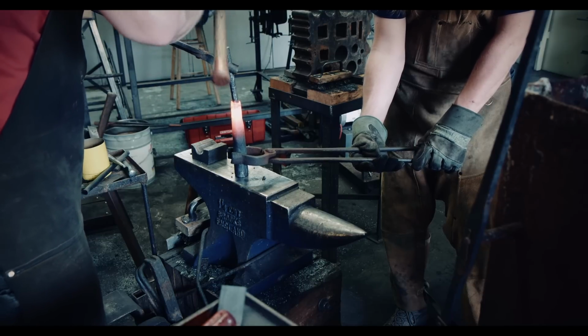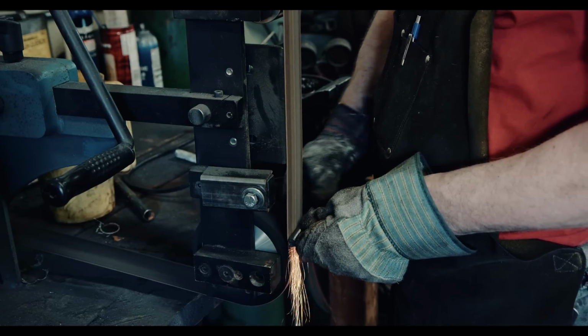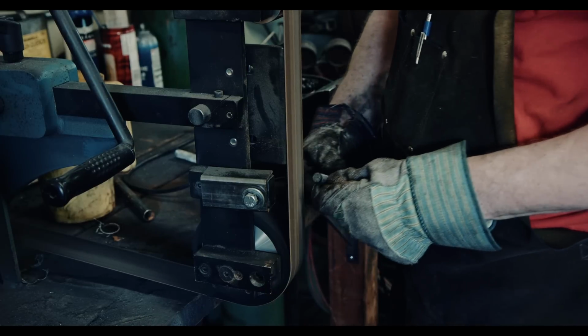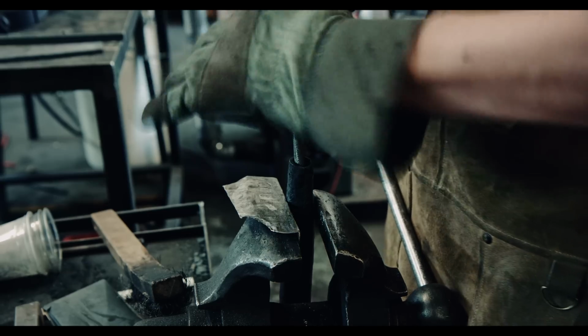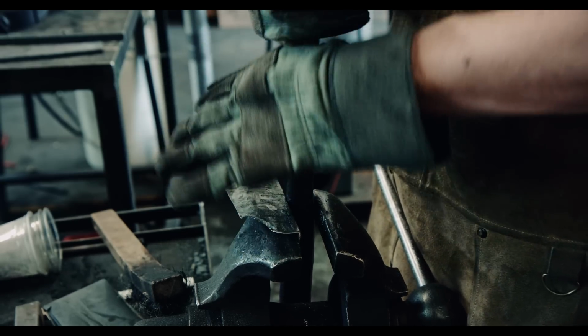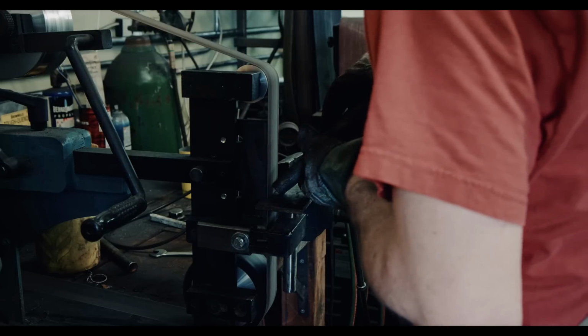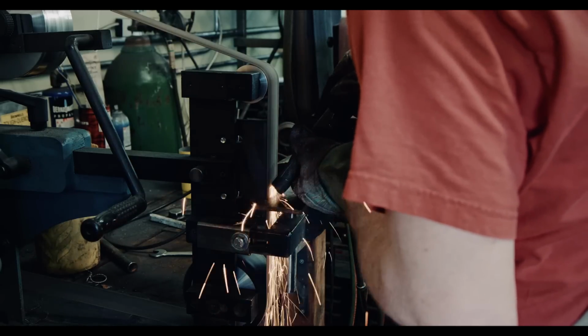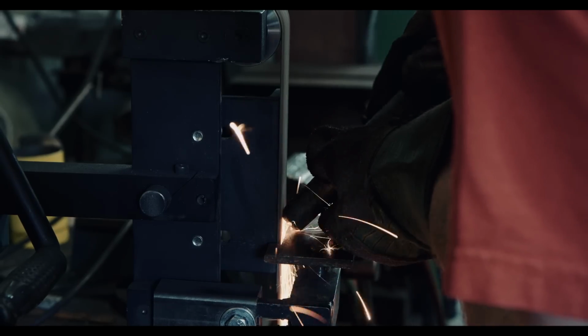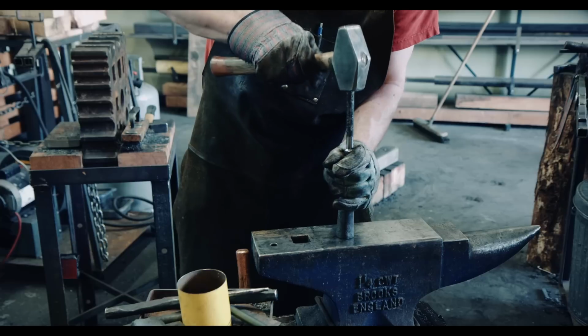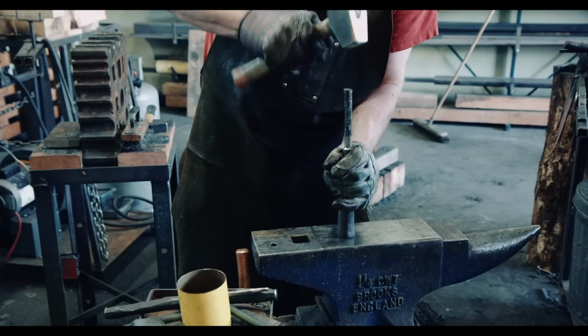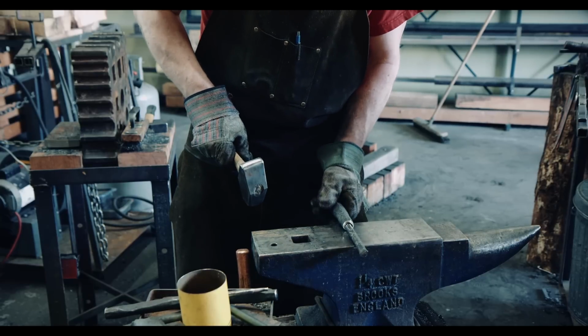To prepare for welding, both surfaces need to be cleaned and free of scale. Also, to create a smooth transition from the socket to the core, we need to scarf the socket, and that will prevent a visible seam and step we would get otherwise. Once everything fits tightly together, it is time to go back to forge welding.